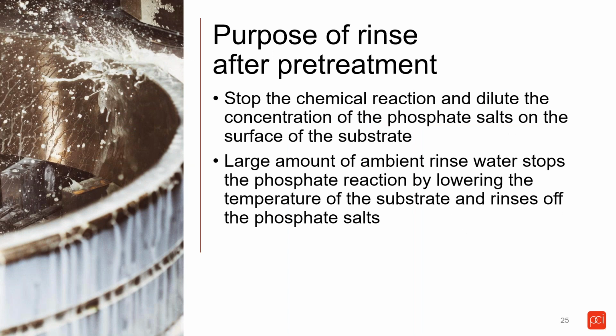Next slide, please. So after you pretreat your part, there's still inorganic salts on the surface, and once you get out of a zinc phosphate stage, for example, those usually operate at 125 degrees. So the rinse will get rid of those inorganic salts as well as stop the zinc phosphate reaction from still going, because the rinse will drop the temperature and stop the reaction where it's at.